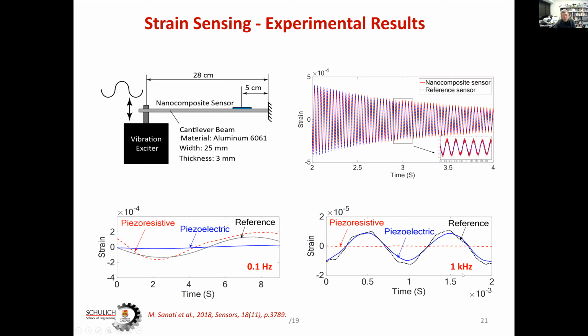The other way around, when you apply this at a very high frequency, for the piezoresistive the bandwidth is not there, whereas the piezoelectric can measure. So what we have done is we combine these two through sensor fusion and are able to achieve fairly decent measurements, both at low frequency and high frequency.